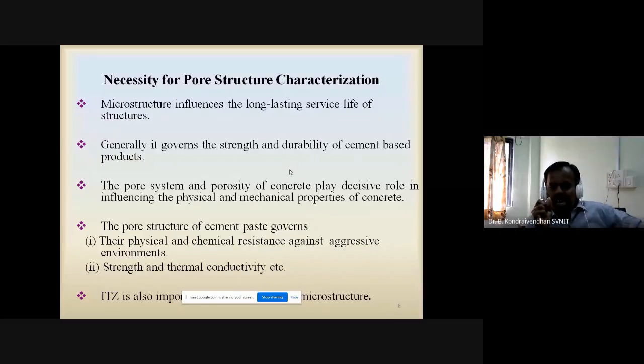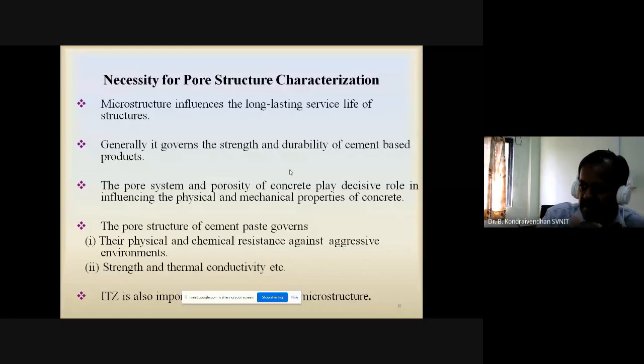Actually, those two things play a decisive role in influencing the physical and mechanical properties of the concrete. The pore structure of the cement paste mainly governs the physical and chemical resistance against the aggressive environment, strength and thermal conductivity. Apart from that, ITZ is another important parameter, that is the interfacial transition zone, the space between the cement matrix and aggregate, which also comes under this microstructure.